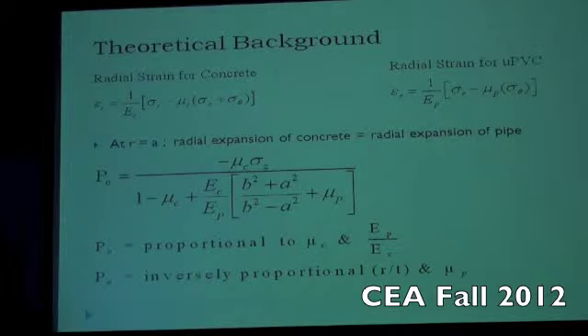Okay, the radial strain for concrete is as follows: epsilon r is equivalent to 1 divided by the modulus of elasticity of concrete times the radial stress minus the concrete Poisson's ratio times the axial stress and the angular, or tangential, stress. And the radial strain for the UPVC is equal to 1 divided by the modulus of elasticity of the plastic multiplied by the radial stress minus the Poisson's ratio of plastic multiplied by the angular stress of the PVC.